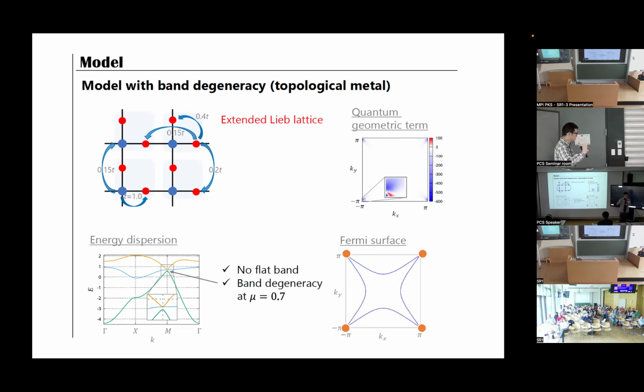So actually, we avoided studying flat band systems because we would like to distinguish the ferromagnetic fluctuation due to the quantum geometry from flat band ferromagnetism. Okay, but anyway, even in the presence of the long range hopping, the band degeneracy is robust in this model because the band degeneracy is protected by the four-fold rotation symmetry. So when we set the Fermi level at the Dirac point here, we obtain the Fermi surface like this. In this case, we can see the large Fermi surfaces connected at the Dirac point here.